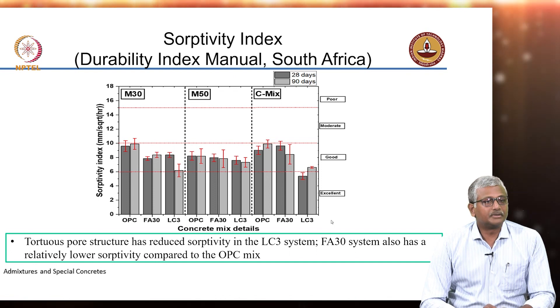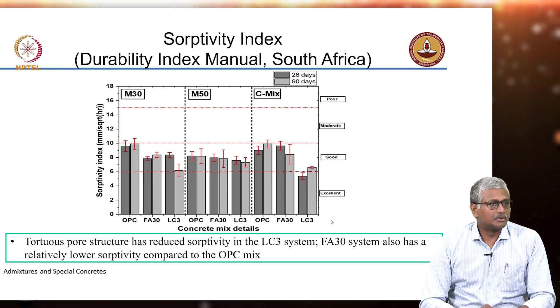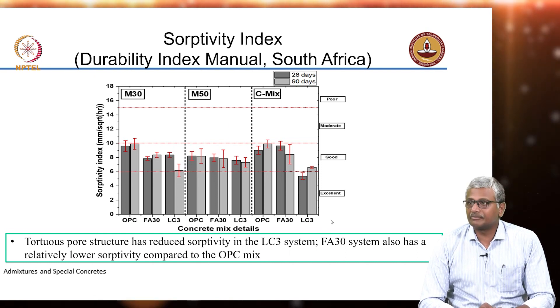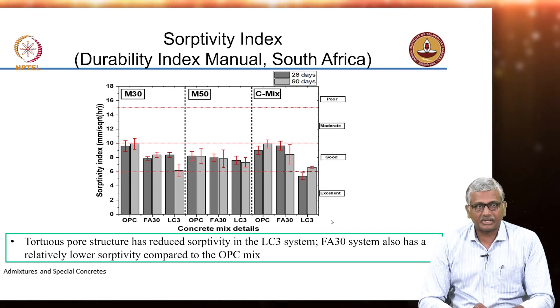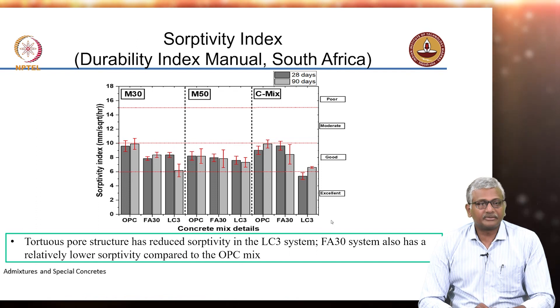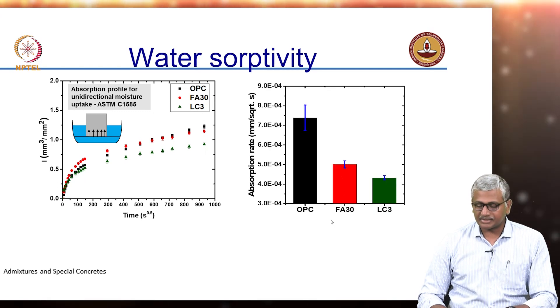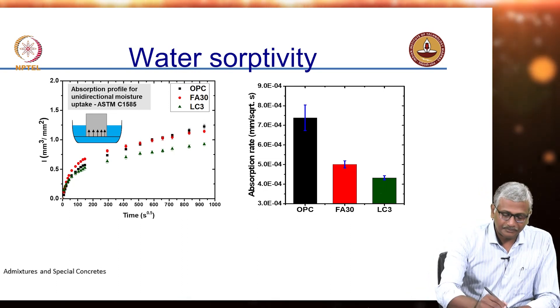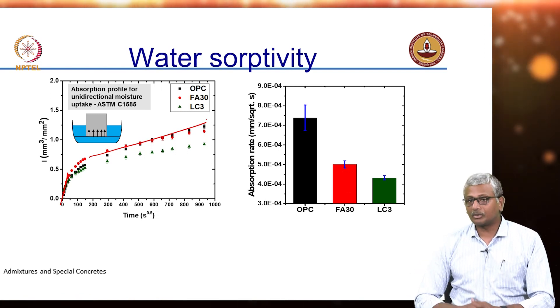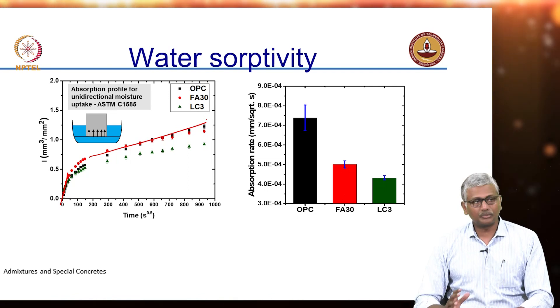We were discussing the performance of limestone calcined clay cement (LC3) and concrete prepared with it, in comparison with ordinary Portland cement and 30% fly ash replaced Portland cement. While the strength performance was almost equal, there was a clear distinction in durability characteristics, especially those measured with electrical methods pertaining to chloride exposure. In water sorptivity studies, the secondary absorption rate clearly shows the benefits of LC3 and fly ash based systems compared to OPC systems.